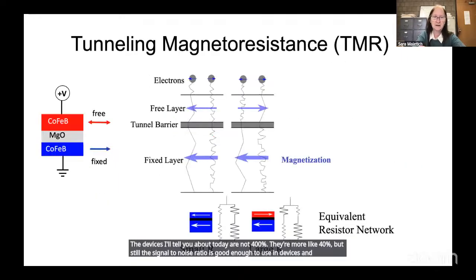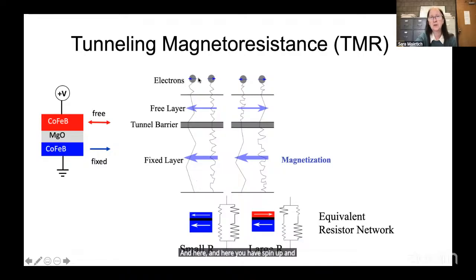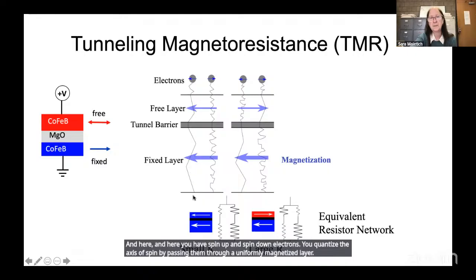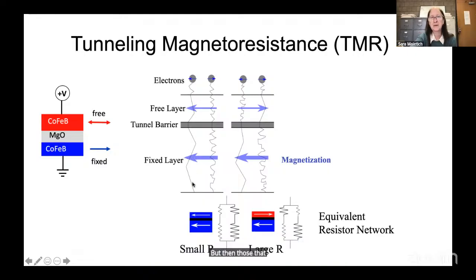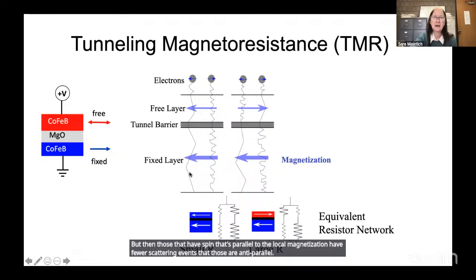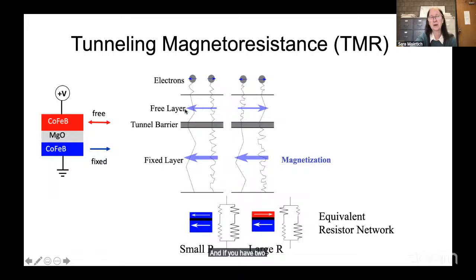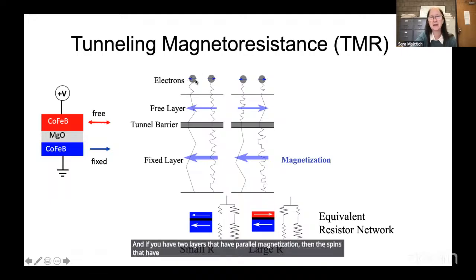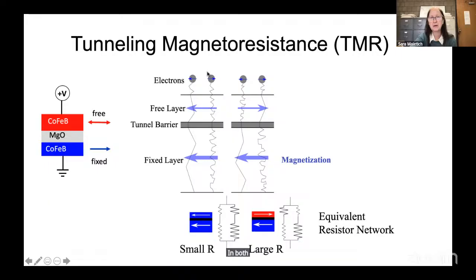And again, another way to look at tunnel magnetoresistance is to think about what happens to the electrons that are passing through. And here you have spin up and spin down electrons. You quantize the axis of spin by passing them through a uniformly magnetized layer. But then those that have spin that's parallel to the local magnetization have fewer scattering events than those that are anti-parallel. And if you have two layers that have parallel magnetization, then electrons that have spin parallel to that will have relatively little scattering in both layers, and the ones anti-parallel would have a lot of scattering.